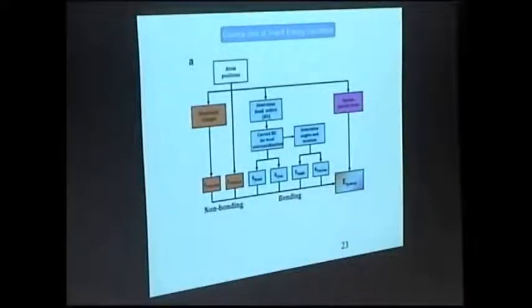And here's a simplified vision of the algorithm that we use to calculate things with ReaxFF. First, you have atom positions, then you determine the charge using the equilibration. Then you determine the bond orders to see who is connected to who.